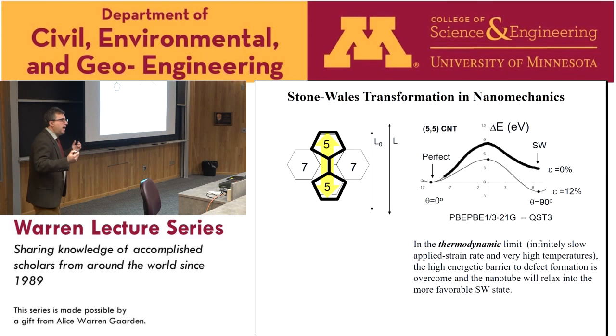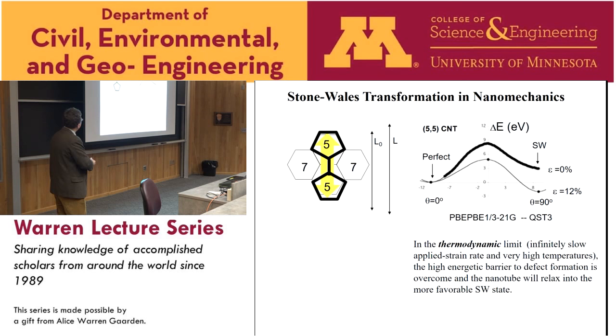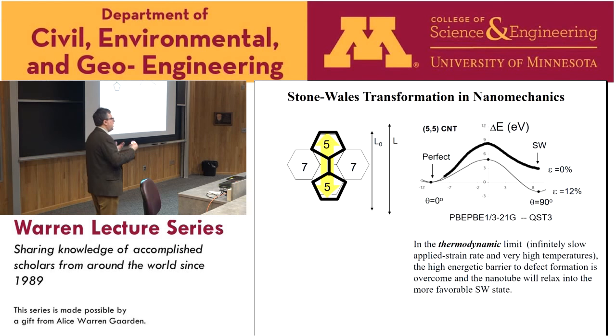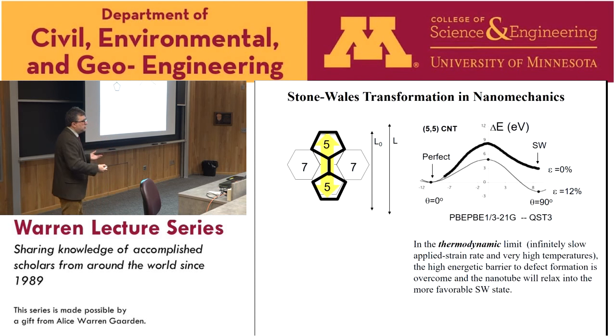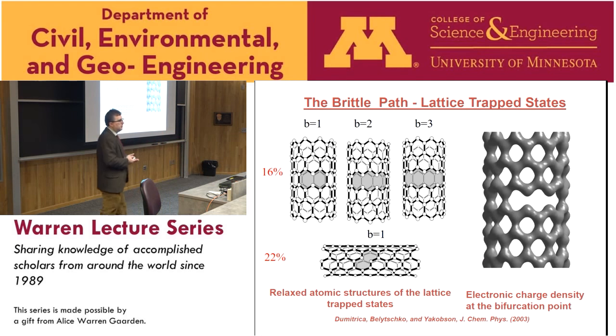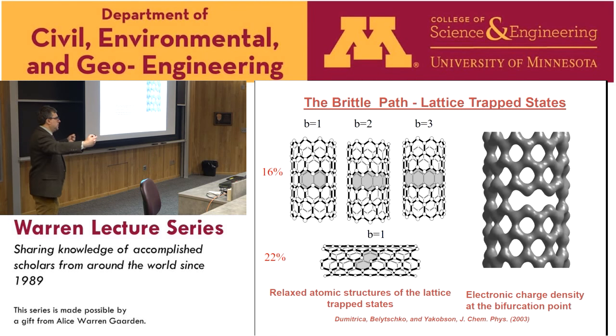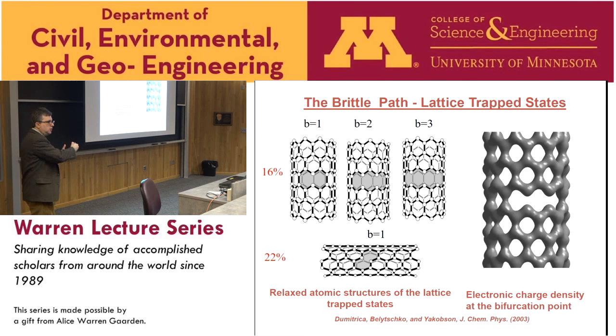If we are stretching the structure, this barrier is lowered — approaching maybe 3 electron volts from 12 eV. So this transformation becomes possible, but it's still a rare event that requires temperature to jump over this barrier. Therefore, we considered the alternative fracture process at the atomistic scale, which is a non-thermal process — fracture can happen without the aid of temperature. So one process is thermal (Stone-Wales) and the second would be fracture. We will be looking at when this fracture would happen.